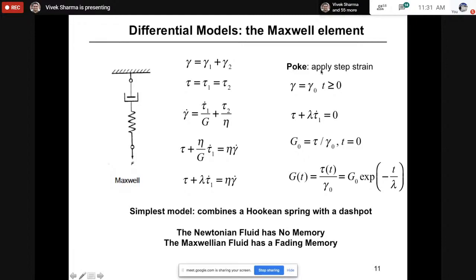Now if you apply a step strain, you just pull it by a certain amount, and then you stop, once you stop, the gamma dot becomes zero, and you're left with this simple differential equation. If we solve this differential equation and define modulus as stress over strain, this gives you essentially the idea that if you are able to measure stress as a function of time, the amount of stress required to maintain that strain is going to decay exponentially. And the decay constant is this time scale called relaxation time. This relaxation time, in some sense, is the ratio of viscosity to modulus, and so contrasts the viscous and elastic effects.